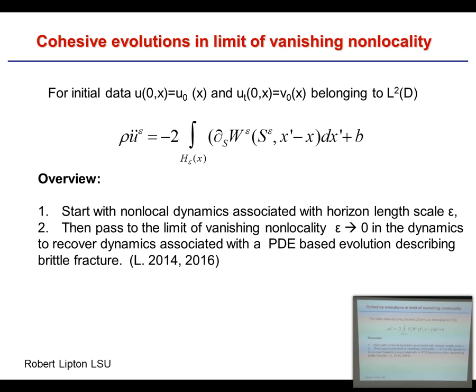Thresholding things: anything with alpha bigger than one half is called a fracture — heuristically, not rigorously, but useful for numerical analysis. This is how we gauge the size of the place where there's dynamic instability — it gets smaller as the non-local horizon gets smaller. This is a consequence of Gronwall's inequality for the dynamics: the kinetic plus elastic energy is less than the energy put into the system, and from our fracture toughness assumption, it is much more costly to have unstable bonds over a large domain, so they concentrate to a smaller region.